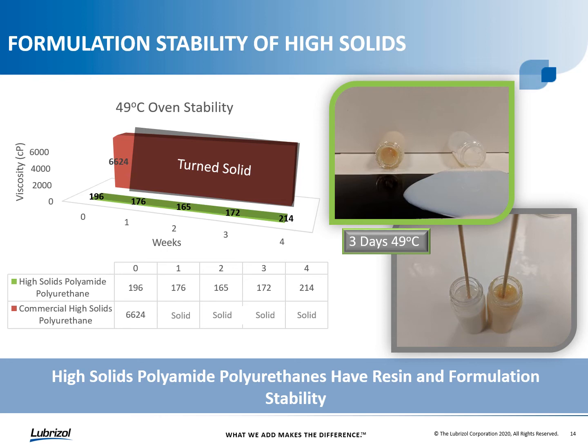And then in the data chart, you can see, again, with the commercial product, we started out at over 6,000 centipoise viscosity. And within just a couple of days, it had completely solidified, whereas the high solids PUD remains stable and very low in viscosity for the 4-week duration of keeping it in the oven at 49C or 120F, having very good package stability.